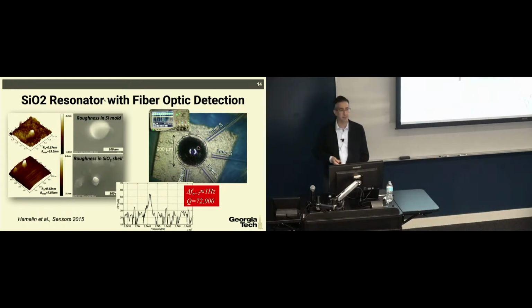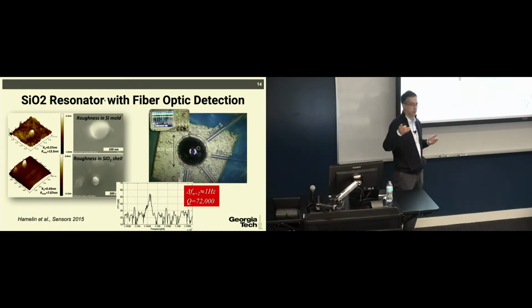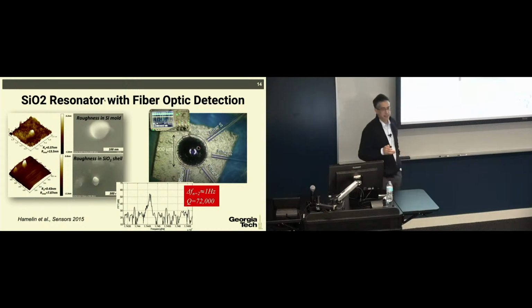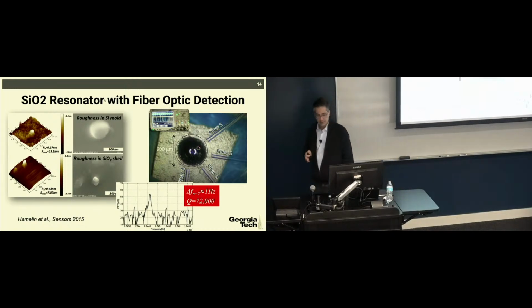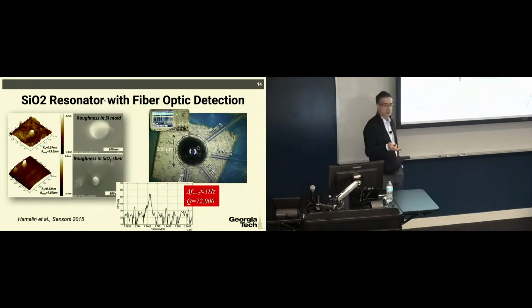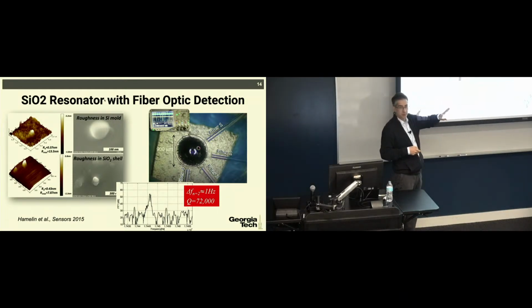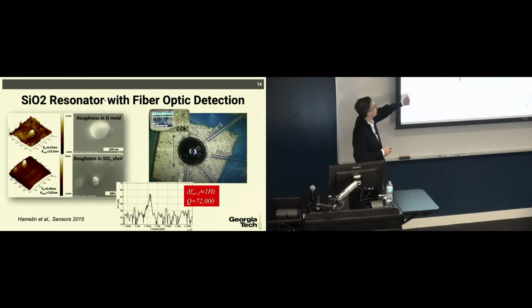It was about 72,000. And this is when we had already measured Qs on the order of 1 million out of silicon resonators. We were expecting the Q in silicon dioxide to be higher just because the thermal expansion in silicon dioxide was much smaller than silicon, and because of that, the thermoelastic damping losses would have been less. So we started looking into surface losses. Remember, surface loss could be a dissipation mechanism.